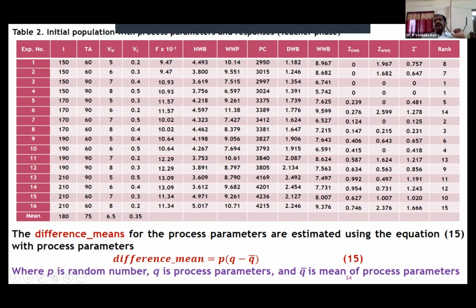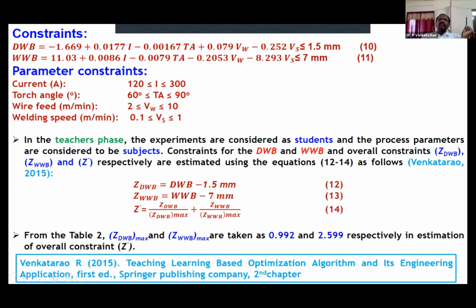Simply I will tell you how to find out the constraint first. Generally here we have taken two constraints, for the depth of weld bead and the width of weld bead. So the constraint of weld bead: depth of weld bead minus 1.5, and width of weld bead minus 7. Based on these constraints, depth of weld bead should always be less than 1.5 mm, and width of weld bead should always be less than 7 mm.